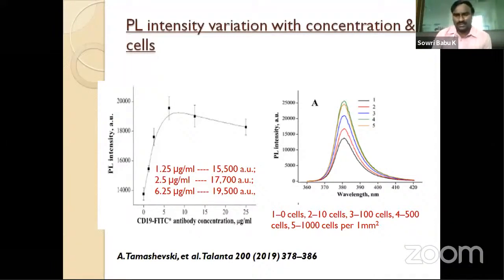Okay. So in the picture on the right side, they have also checked how the PL intensity varies as they increase the cells. For 0 cells, the second peak, the red peak, indicates the PL intensity for 10 cells, 100 cells, 500 cells, and 1,000 cells. Okay, so there is enhancement in the peak intensity as the cell concentration increases.